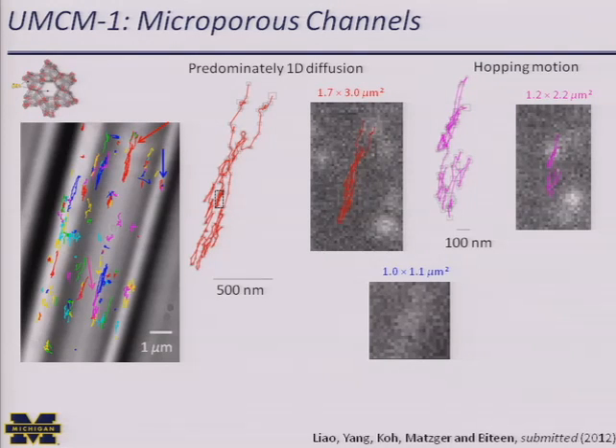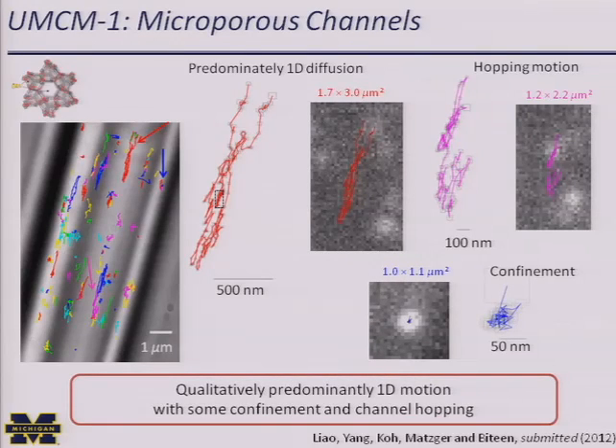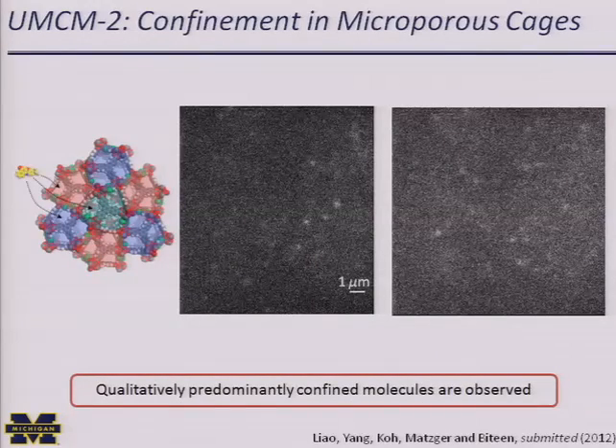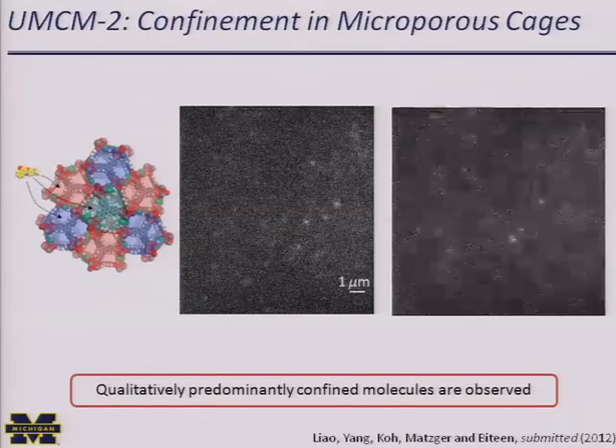Finally, down here, this blue molecule, which is just a tiny dot, is showing us a confined particle that is not moving over the course of the image acquisition. In UMCM2, on the other hand, there's no predicted channels or planes. So the only molecules that we see end up being trapped. They diffused very slowly into the material, and they are trapped for some time.